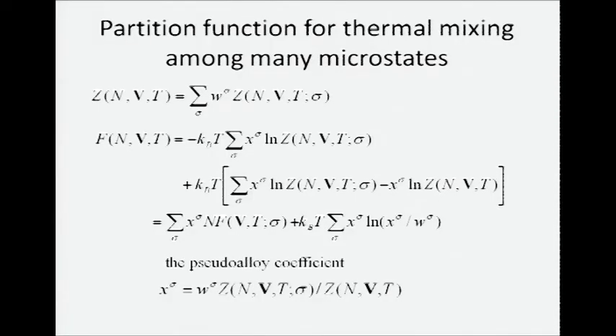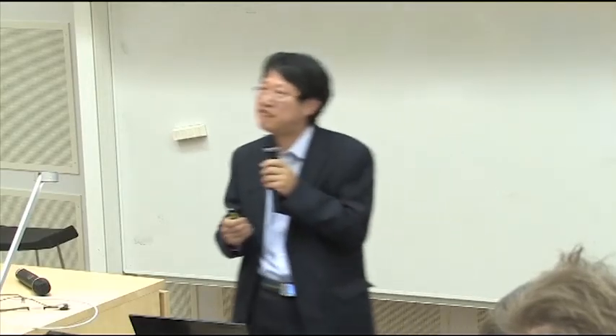You can simply write the partition function as a summation of individual magnetic states, talking about limiting to spin up or spin down flipping. If you have a supercell with 100 atoms, doesn't matter, then you have spin configurations of about 2 to the power of 100, but that's huge. You might calculate using a much smaller one.